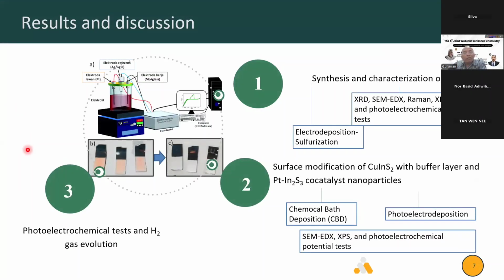For the first part, this is the set of measurements. We use the potentiostat to measure the photocurrent, and this is the setup of photoelectrochemical water splitting. We use sodium sulfate as the electrolyte, with the similar counter electrode, reference electrode, and working electrode. The working electrode is our photocathode.